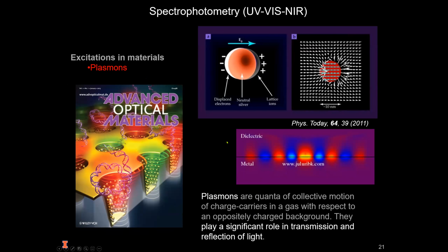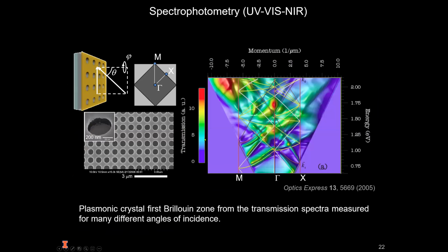In this example, we wanted to use this plasmonic crystal to fabricate a chemical sensor. As part of this project, we used transmission spectra collected for many angles of incidence to map the crystal's first Brillouin zone before and after exposition to our target chemical. With that, we could characterize the response of our sensor to that chemical and then use it to fabricate the device that we wanted. The lines here on this picture indicate calculated plasmonic modes, and you can see a very good agreement between the measurements and the calculations.